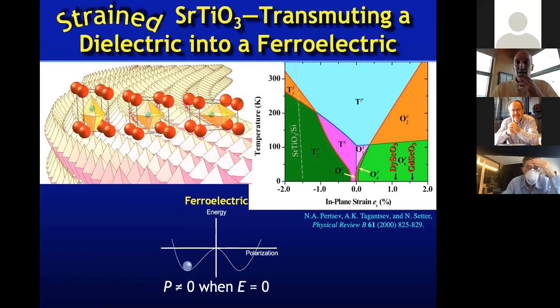And so this realization was made by a Swiss and Russian group, and they predicted the effect of biaxial strain, which is the horizontal axis that's imposed by a substrate, on strontium titanate. And it's a very colorful diagram, as you can tell, but the things to pay attention to are the superscripts. So the superscript P means that the material is paraelectric. And that's where strontium titanate is normally. Strontium titanate normally has a center of symmetry, so it cannot become ferroelectric.